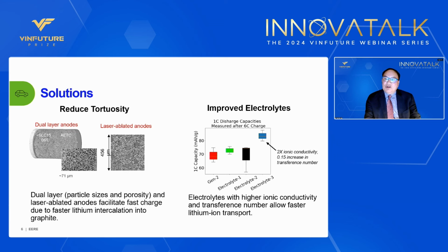So this plot shows you what happens after you do 6C charge to a single cell with different electrolytes. We call them Gen 2, electrolyte 1, electrolyte 2, and electrolyte 3. And after that, you do a 1C discharge to measure the capacity of the cell at the 1C rate. And you can see the one with 2 times ionic conductivity and 0.15 increase in transference number has the most specific capacity. So that tells you improved electrolyte can allow much faster charge.